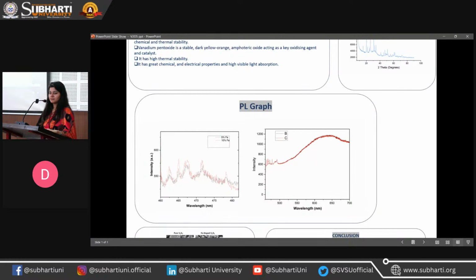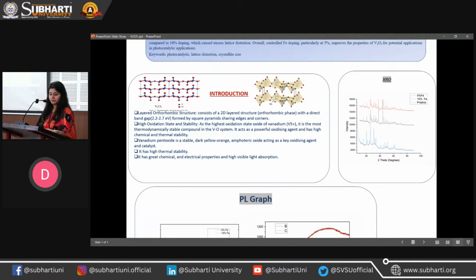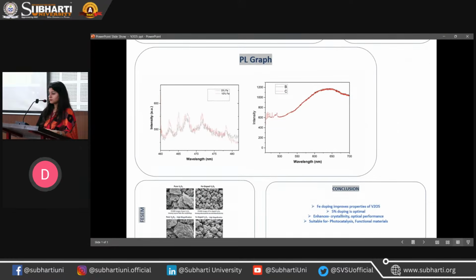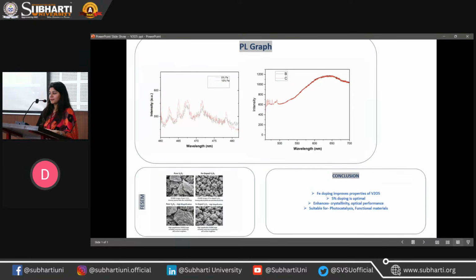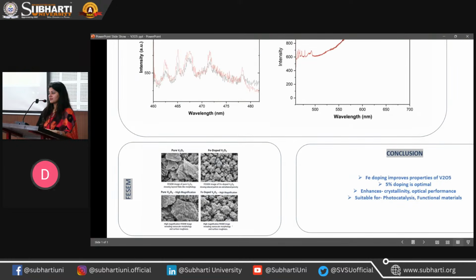This is the XRD graph. From XRD analysis, we confirmed the orthorhombic structure of V2O5. After doping, the crystalline size decreases and lattice strain is introduced. The PL graph shows a decrease in emission intensity, which indicates reduced electron hole recombination and improved charge separation. FESEM image reveals a more uniform and improved structure after the doping.